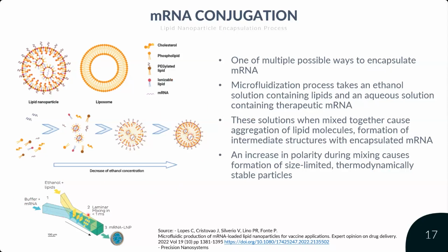As you mix them in microfluidic channels and your ethanol concentration goes down, these mRNAs start to form micellar structures that are of nanoparticle size and contain your therapeutic mRNA. And this increase in polarity during mixing causes formation of size-limited, thermodynamically stable particles.